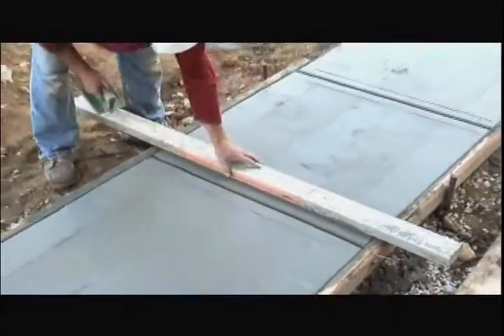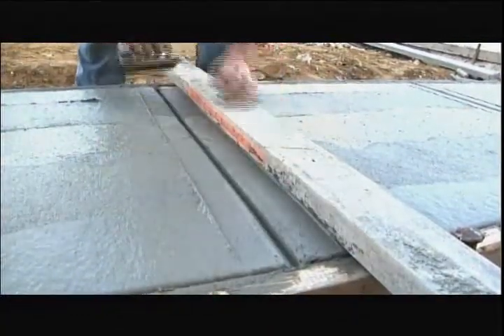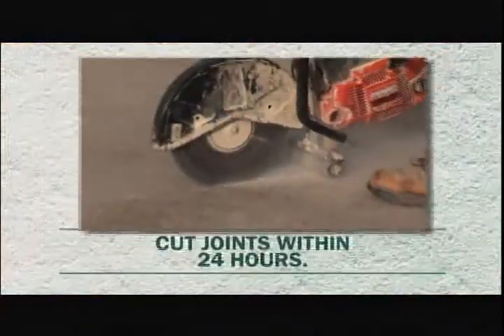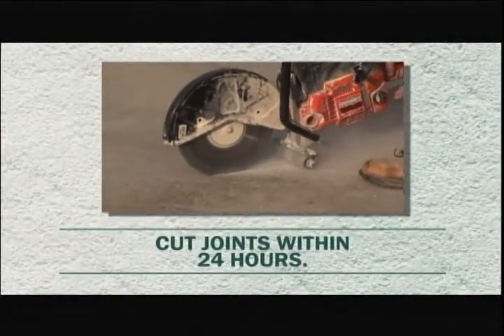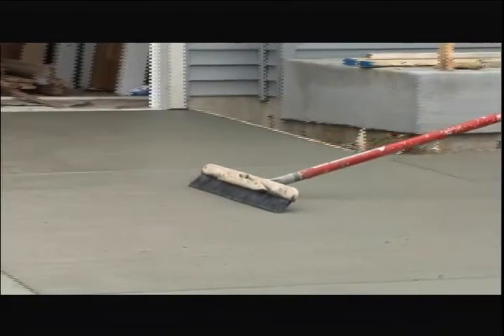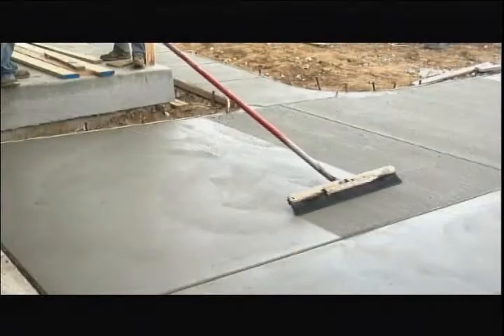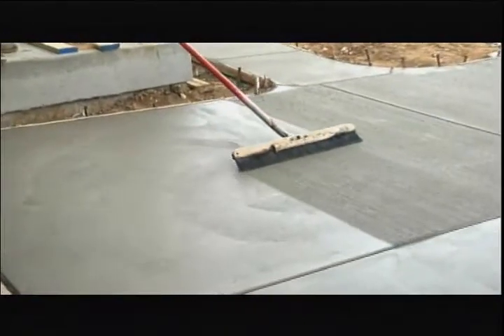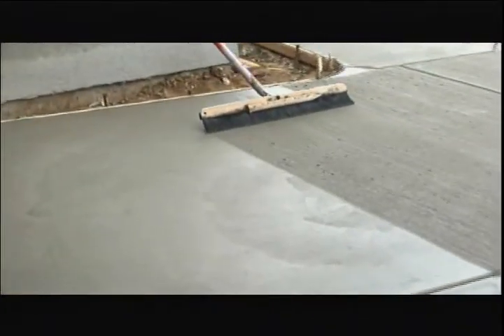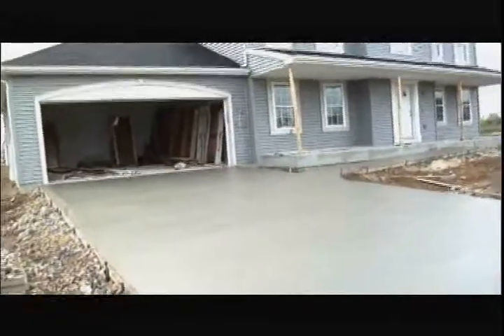Contraction joints are made with a hand groover or by inserting strips of plastic, wood, metal, or preformed joint material into the unhardened concrete. Saw-cut joints can be made after the concrete is sufficiently hard or strong enough to prevent raveling. Brooming before the concrete has thoroughly hardened creates a slip-resistant surface. However, it should be sufficiently hard to retain the scoring impression. A broom finish for exterior concrete is ideal and helps ensure the contractor is finishing the slab properly and not overworking it. Absolutely no finishing operation should be performed when there is excess moisture or bleed water on the surface.